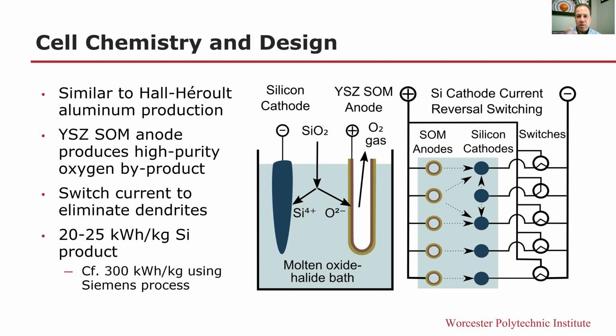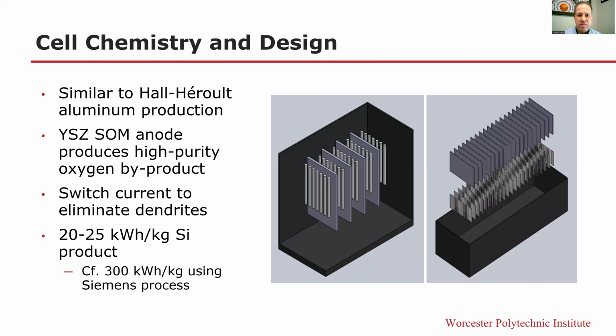So to avoid that, we periodically reverse the current, and in order to maintain a large high current bus and relatively low cost for the overall plant, what we do is we throw a switch periodically for one or more of the cathodes at a time, reversing the cathode to anodic potential, so that instead of plating silicon, we dissolve silicon, and that roughness dissolves rapidly, and then we can resume deposition again. This comes at a cost of some current efficiency loss, typically about 5 to 10%, so not a lot. But the result is we can grow silicon very nicely.